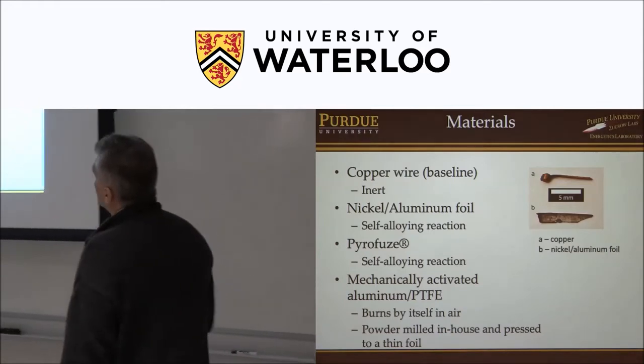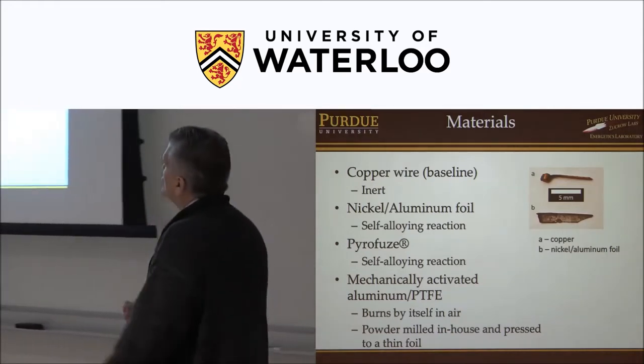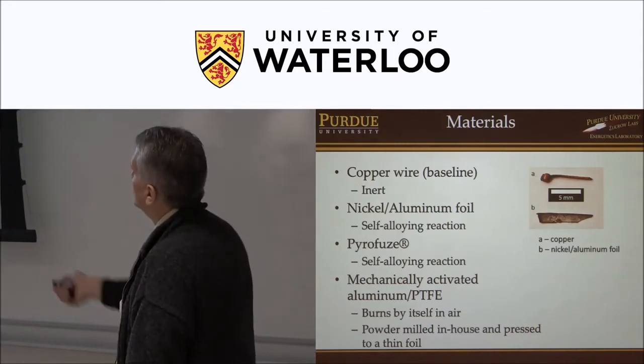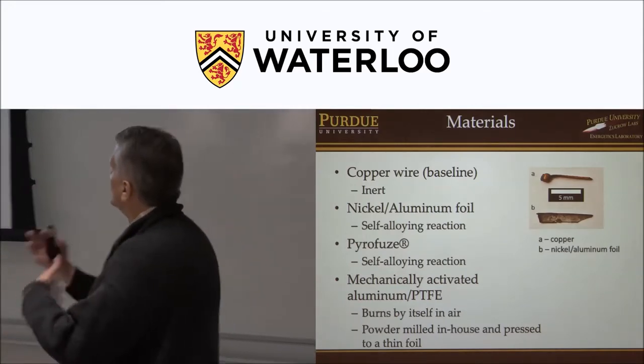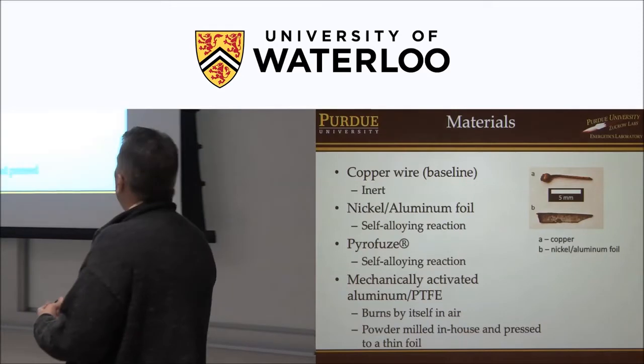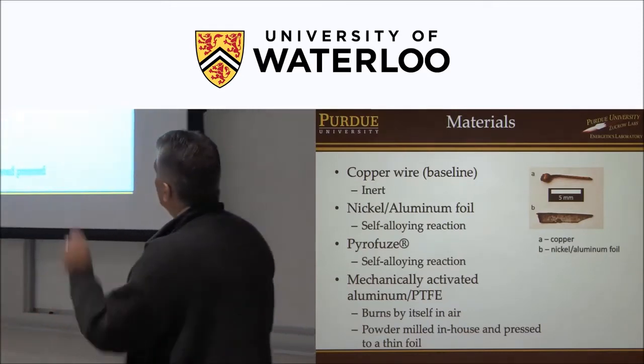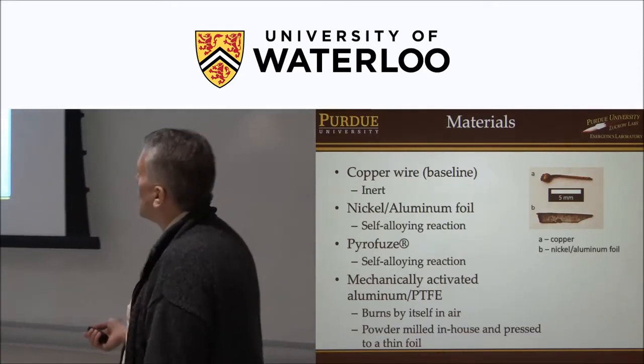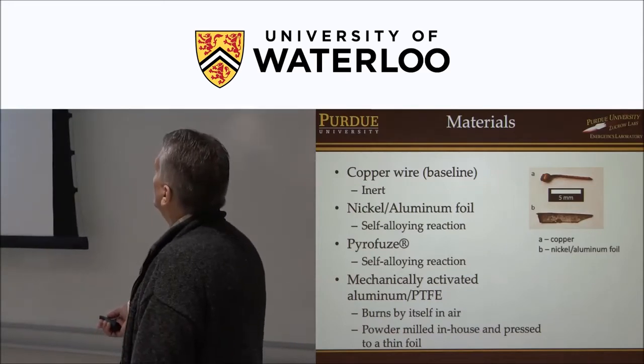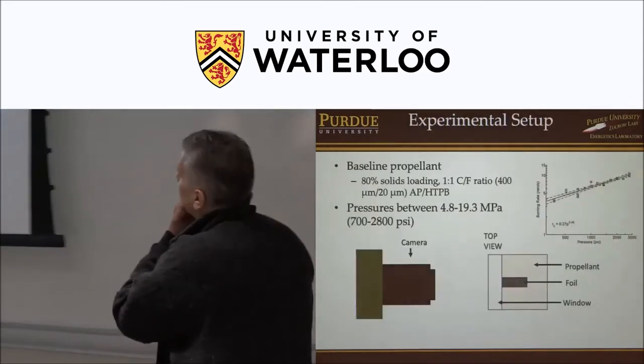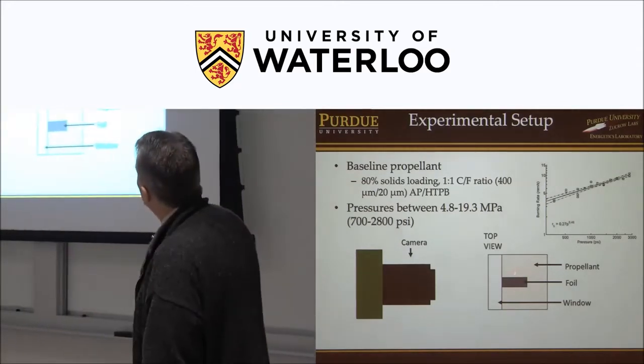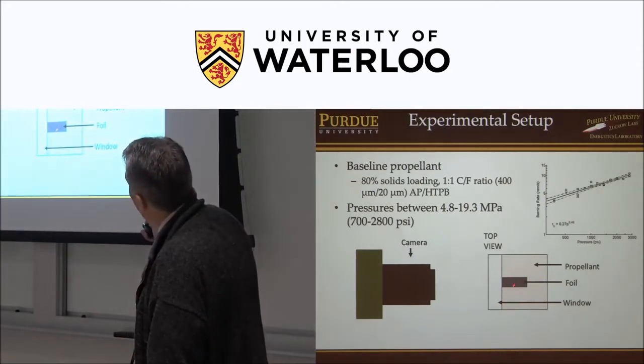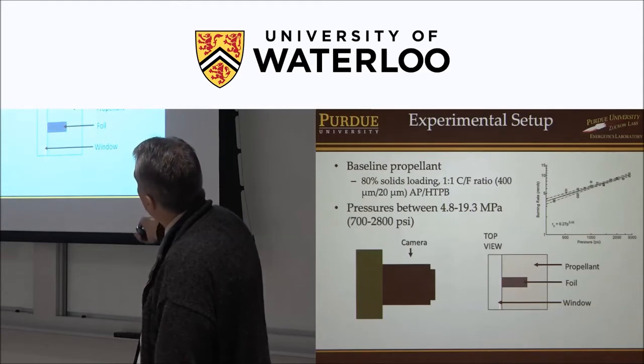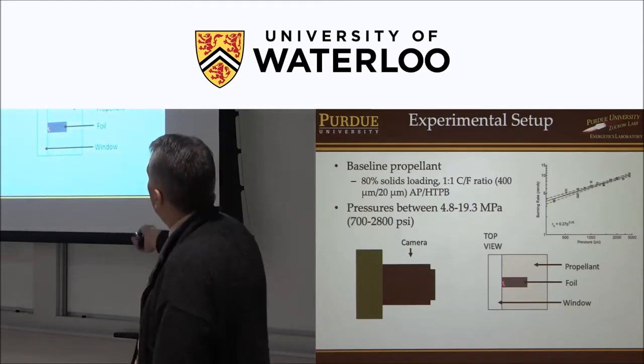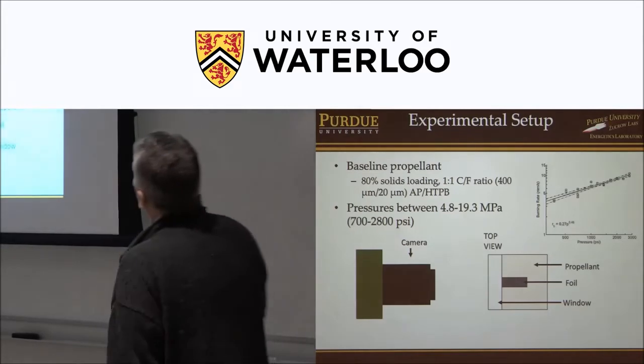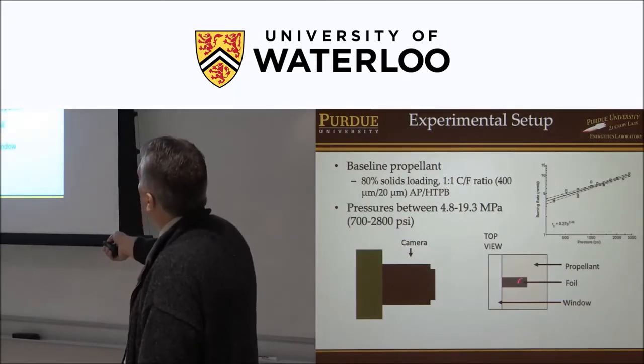Pyrofuze is another intermetallic self-alloying reaction that's used in igniter systems. And then this material, again, it's mechanically activated, so we've pounded, in this case, Teflon inside of aluminum. We made that into a kind of a foil or a wire and put that into a propellant. So how we do the experiment is we have a strand of propellant that we've cast, with this foil or wire. We put a window here so we can see what the effect of that wire or reactive wire is.